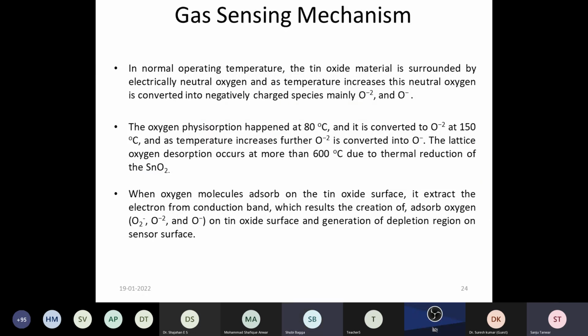Now, the question is how this sensing mechanism happens. At normal operating temperature, the tin oxide material is surrounded by electrically neutral oxygen, and as temperature increases, neutral oxygen is converted into negatively charged species. There are basically two phenomena: one is physisorption, another is chemisorption. Oxygen physisorption happens at 80 degrees centigrade and is converted into O2 negative at 150 degrees centigrade. As temperature increases further, O2 negative is converted into O negative, and at the same time oxygen desorption also occurs at more than 600 degrees centigrade due to thermal reduction of the tin oxide material.